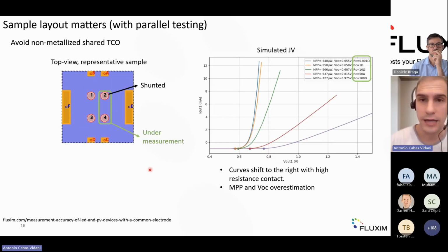Let me show you a quick example. Here we have indeed these 2 pixels. They are under measurement, and one of these pixels is shunted. And on the right, you have simulated JV for pixel 4, so the one that is not shunted, with increasing resistance of the common electrode. You see here the resistance grows from almost 0 up to 100 ohm, passing through values like 1 and 10, which are closer to reality.